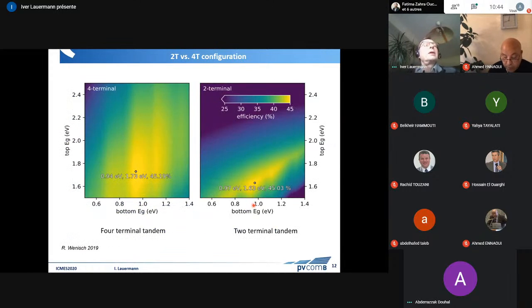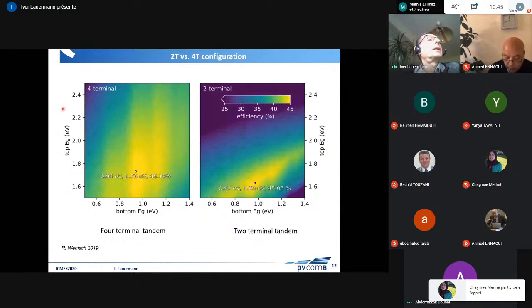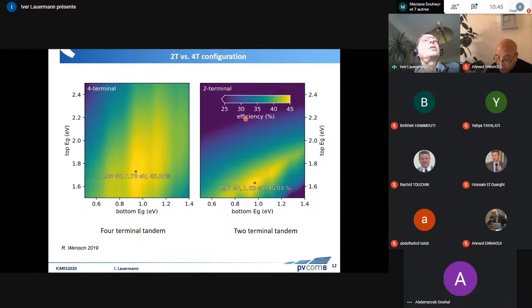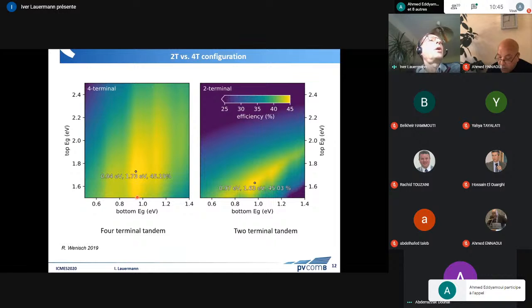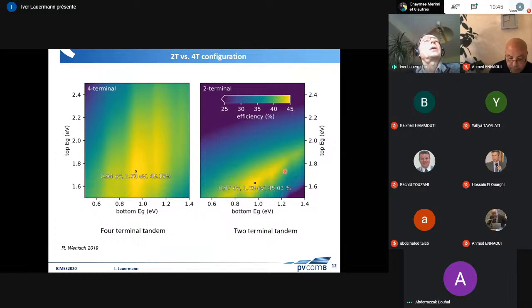So if we look at the efficiency, and here we are comparing the 4-terminal device to the 2-terminal device. We're looking at the band gap of the bottom cell and the band gap of the top cell. And the color scheme gives us the efficiency. So in the yellow part, we go to 45% efficiency, which is very good for a solar cell. We can see here in the 4-terminal tandem, we end up at a combination of 0.94 eV for the bottom cell and 1.7 for the top cell. And it's not too different for the 2-terminal device, but here you can see the sweet spot. This yellow area is much smaller. So you are constrained to a certain combination of top and bottom band gaps.